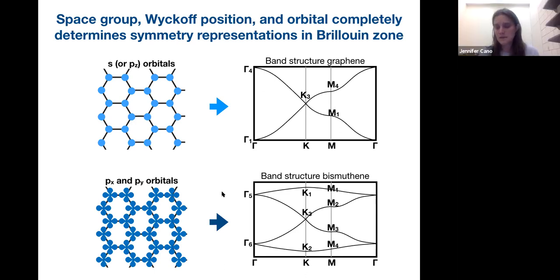Yeah, exactly. So one way to think of it is that we have a rotational symmetry here. If you take our six-fold rotation, and you do the six-fold rotation six times, you get a 2π rotation. And so you'll get some symmetry group where that 2π rotation gives you +1, the identity element, for spinless and -1 if you have spin. And so that gives you a different group structure for both of them. Yeah, and actually, you can always work in the case with spin orbit coupling. It will just give you twice as many labels. They'll be slightly different labels. It will always give you the right labels if you then set spin orbit coupling to 0, but you'll have some extra freedom because there'll be twice as many terms you can write down, roughly speaking. So if you have 0 spin orbit coupling, it's more useful to work in the group which corresponds to 0 spin orbit coupling.